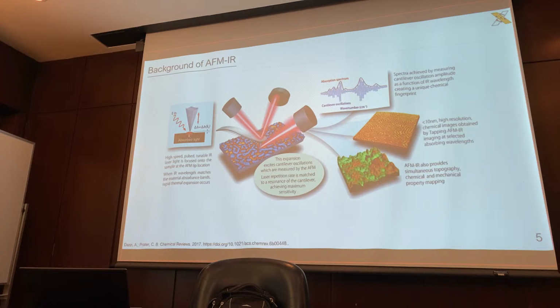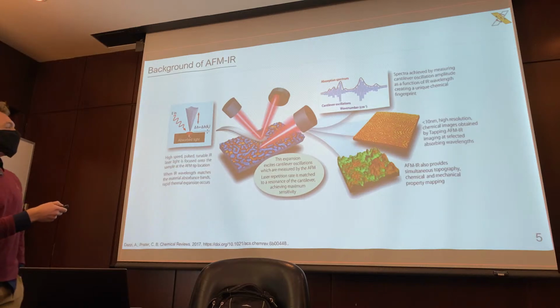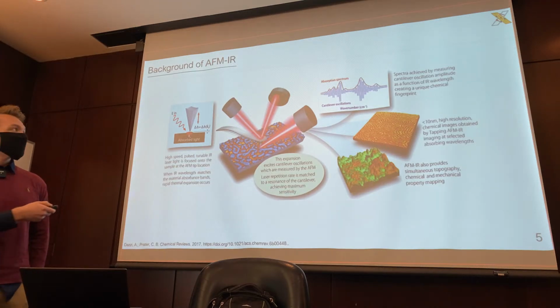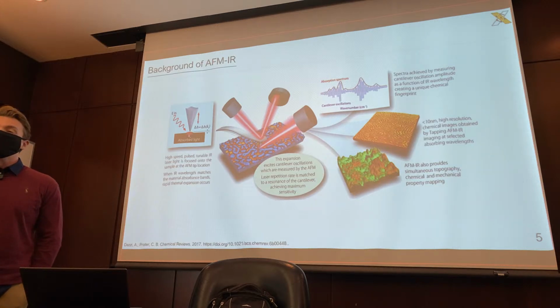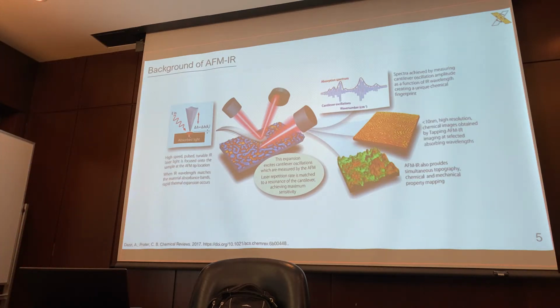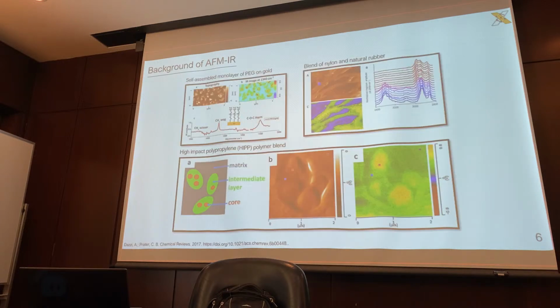Now it detects this thermal excitation or expansion in the form of deflection. And so using this technique, we can create an absorption spectrum from these cantilever oscillations, as shown here. And so this will mimic what you might see in a traditional FTIR spectrum. So this has been used extensively to model different morphological systems in terms of solar cell polymer blends, composites, and blends as found in like nylon, polypropylene, and other industries.